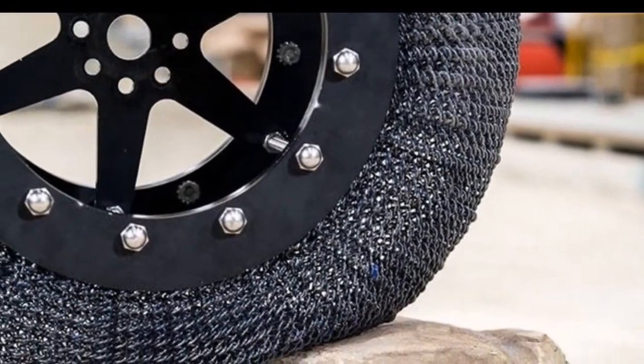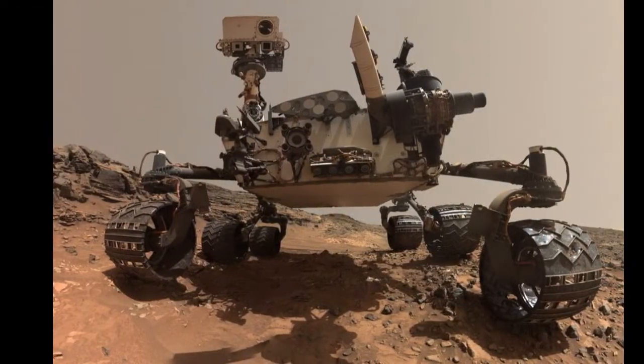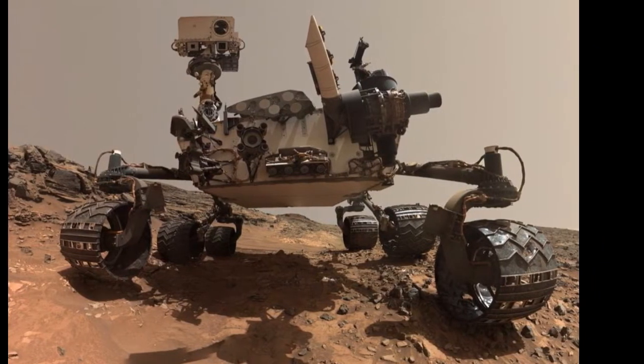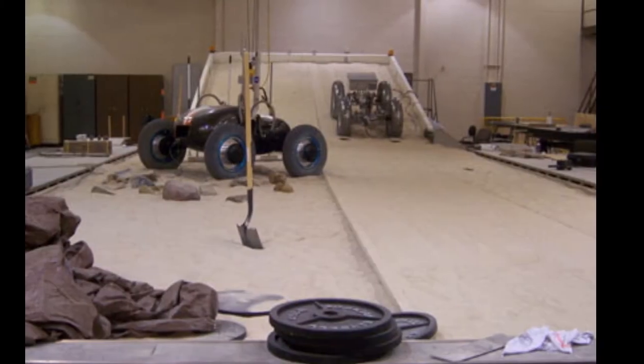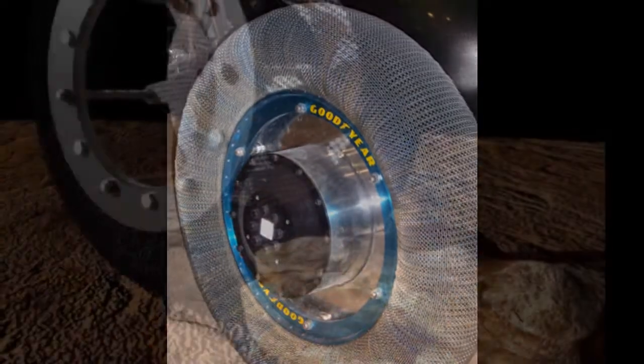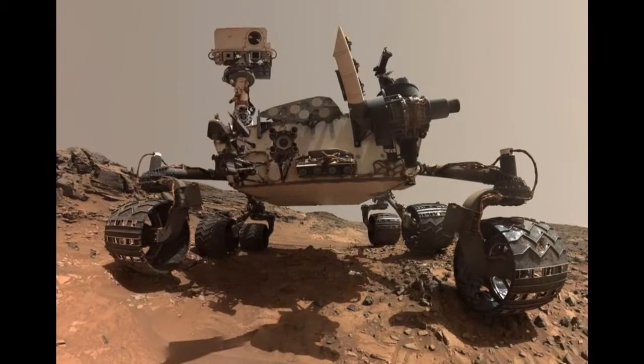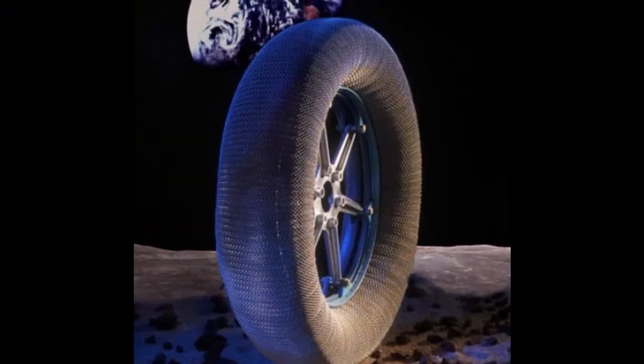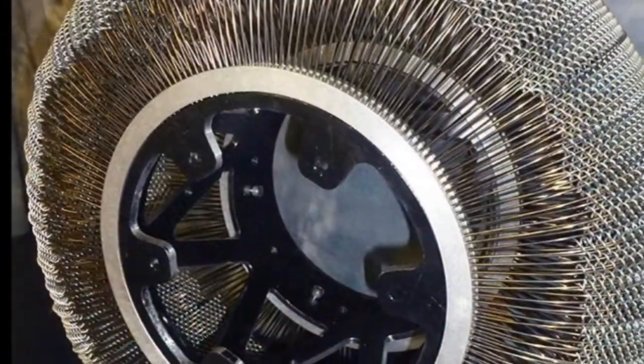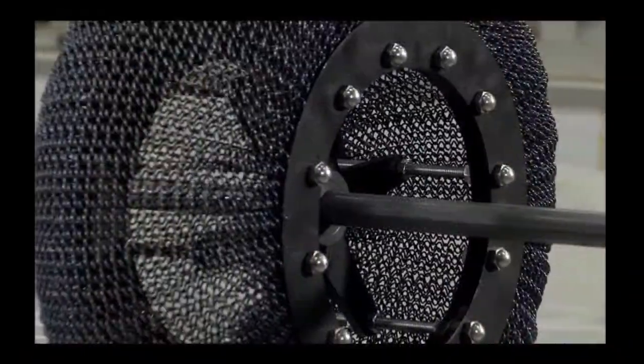Tires with great memory. After years of research, the team settled on a nickel titanium (NiTi) alloy and figured out the best process to form and treat it. Spring steel can only withstand 0.3% of strain, the distance the atoms in the metal shift, before it gets dented and the metal crystals permanently rearrange. The NiTi alloy in question, however, can suffer up to 10% strain, about 30 times better elasticity.